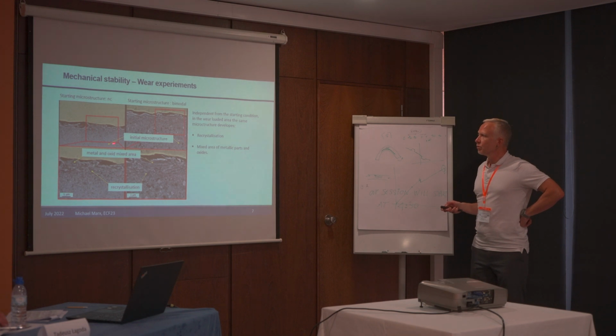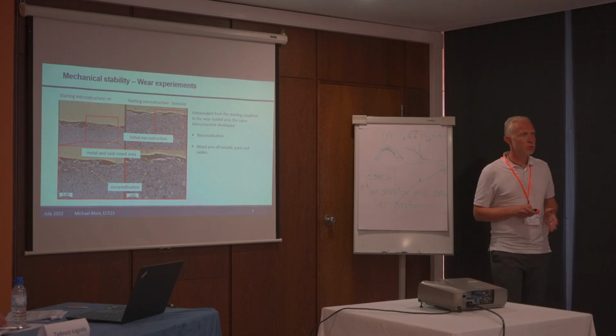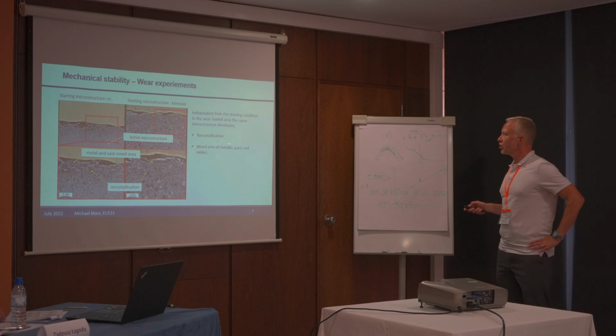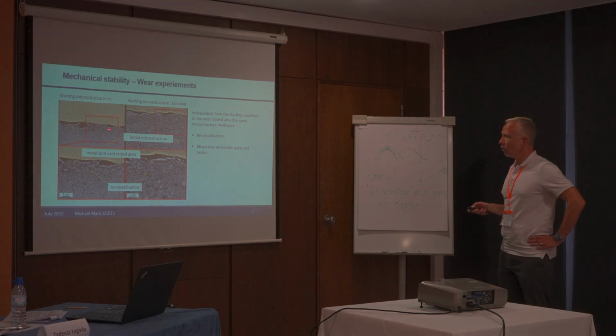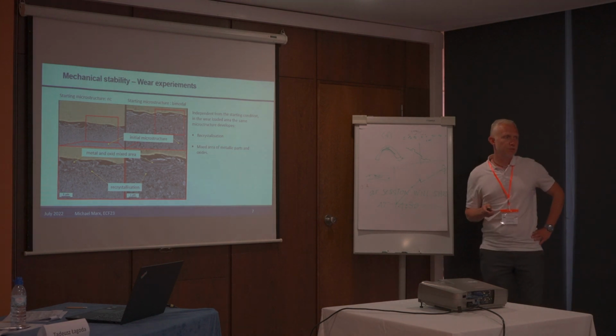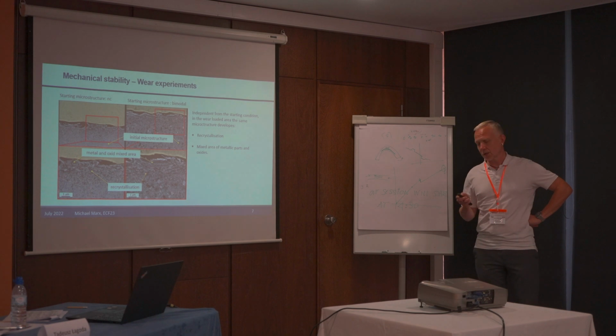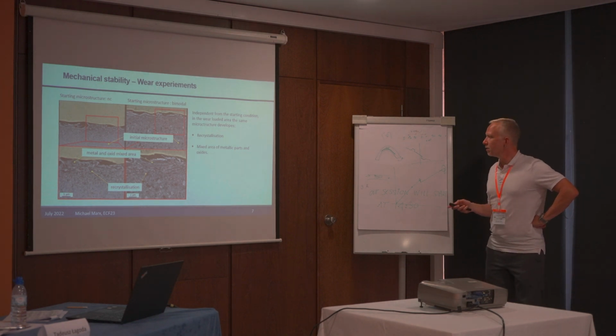For the mechanical stability, we did some wear experiments. We started with two initial microstructures, one nanocrystalline and the other one in the bimodal structure, and we found at the surface in both cases we got the same microstructure. We find recrystallization due to the wear, and we get a mixed area of metallic parts and oxides from the surface mixed in this surface near area.